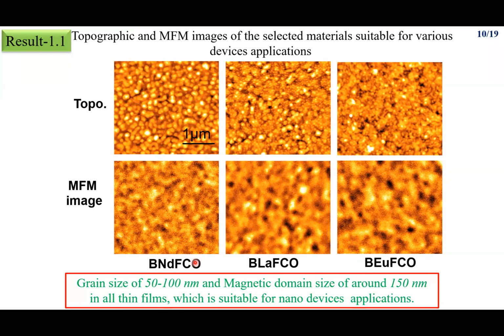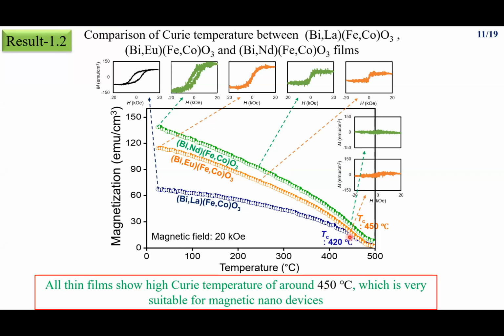So first I considered these three elements and measured their domain size and grain size. I could see their grain size lies between 50 to 100 nanometers and domain size is around 150 nanometers. That is very small in the case of multiferroic thin films, so this is suitable for the device applications. If I think about the Curie temperature, which I observed to be very small in my previous slide, here you can see in my new materials it is around 450 degrees Celsius. That is also very high for the device applications. So considering these two basic parameters, I can say that these samples are suitable for the device applications.